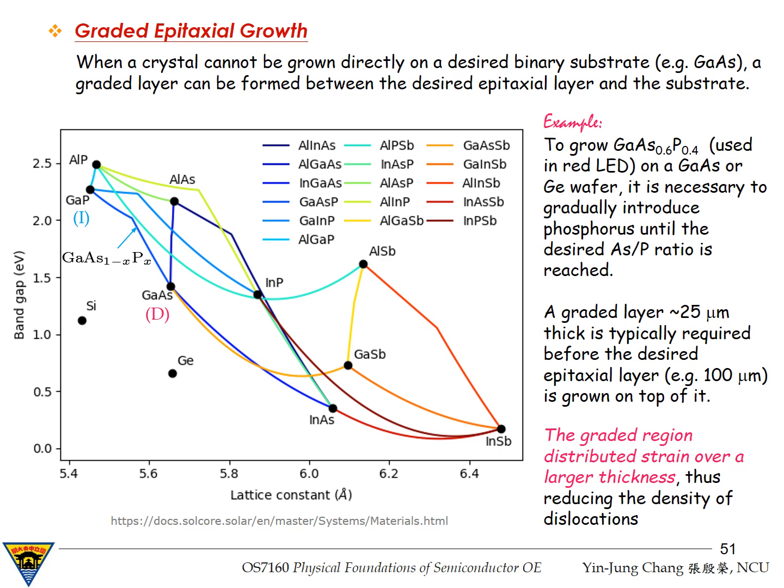And let's look at the diagram on this page again. As we have discussed earlier, different binary compounds lie at different positions in this map. When designing devices such as red LEDs, we choose materials based on band gap. However, we must simultaneously satisfy lattice compatibility. So this is the core engineering trade-off in heterostructure design. The electronic and optical properties depend on the band gap, while structural compatibility depends on lattice constant.